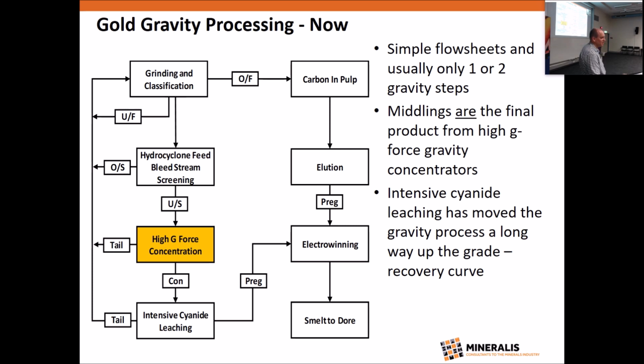So when you combine that with the intensive cyanide leaching on this site through the Acacia reactor, which incidentally was developed at Union Reefs, the gravity process has marched a long way back up towards the recovery end of the grade recovery curve.